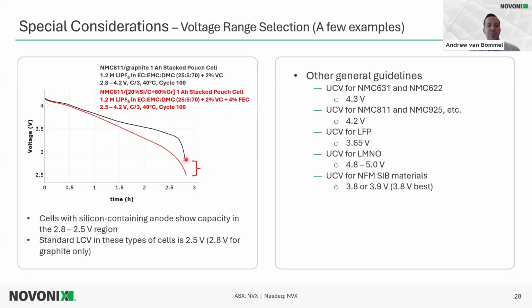And so we know we won't get much capacity past a lower cutoff voltage of 2.8 volts. However, for silicon-containing systems, because of the voltage curve of silicon itself, we see that there's more of a sloping profile at the end of discharge, and there's more capacity that can be obtained between this 2.8 volts and 2.5 volts. So our standard practice is to discharge all the way to 2.5 volts for silicon-containing cells. Of course, unless you want to evaluate a lower depth of discharge. But a full DOD, we would say that's going to 2.5 volts.